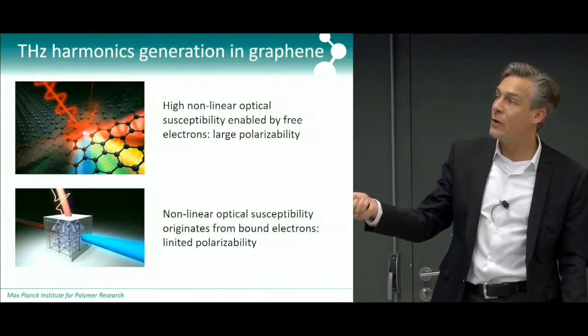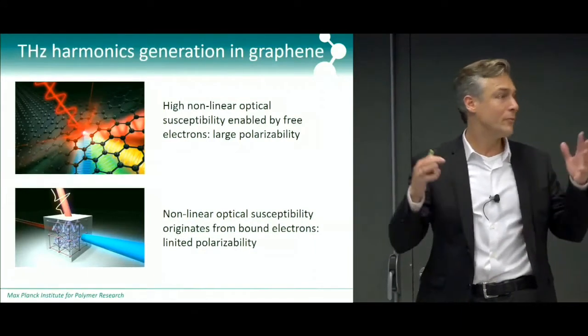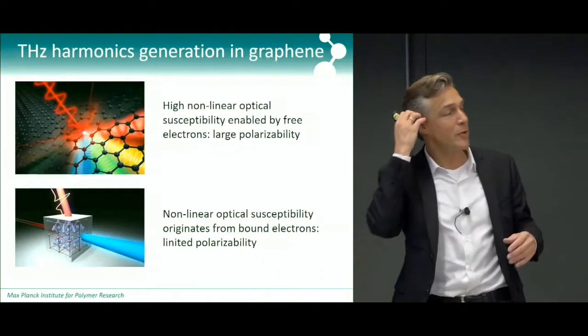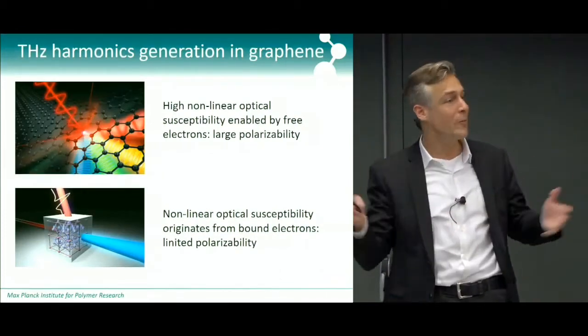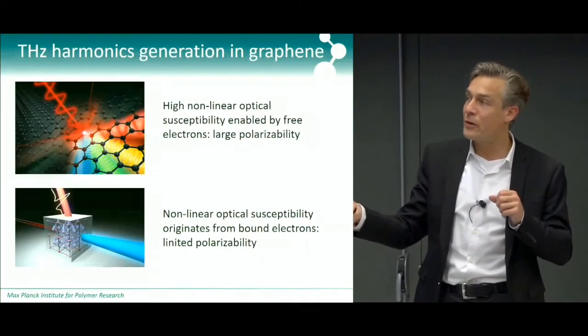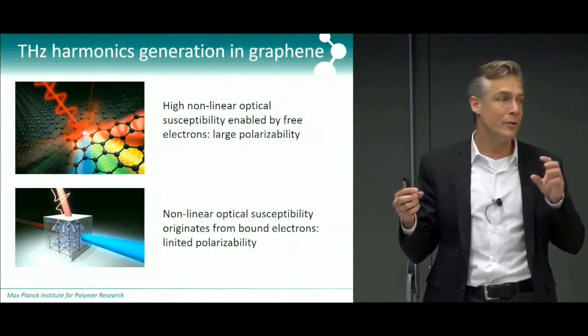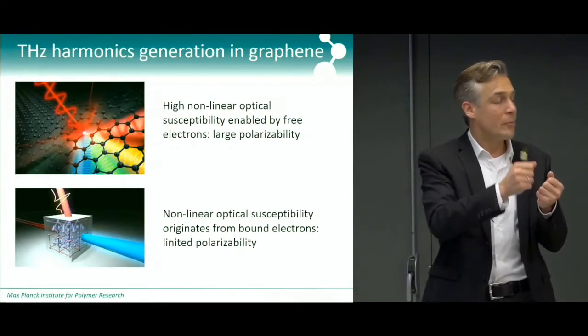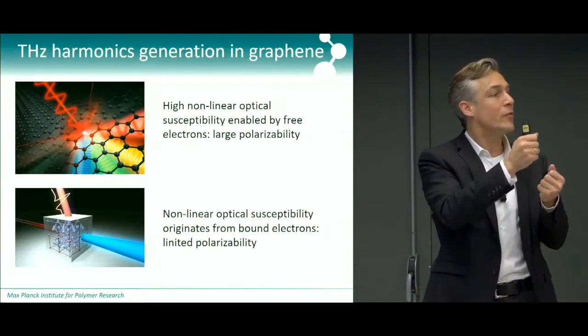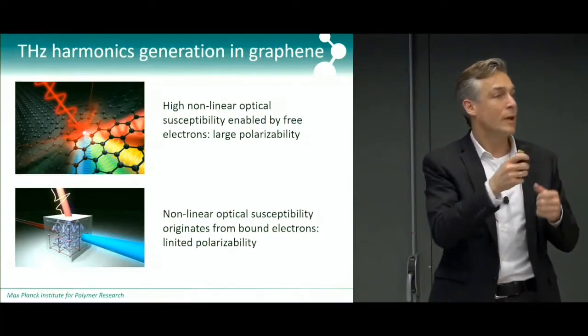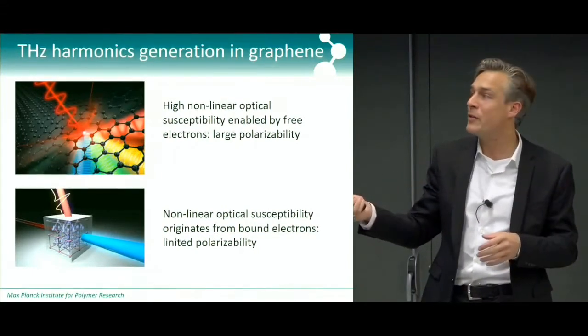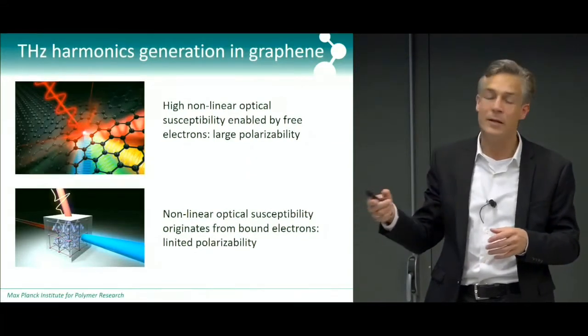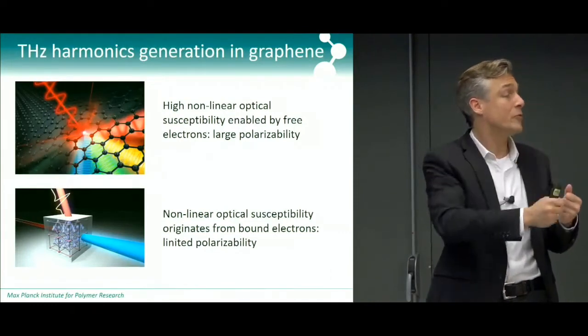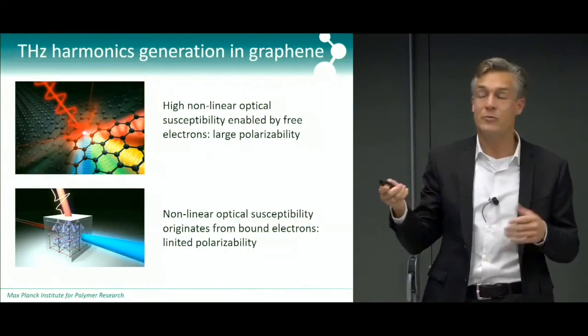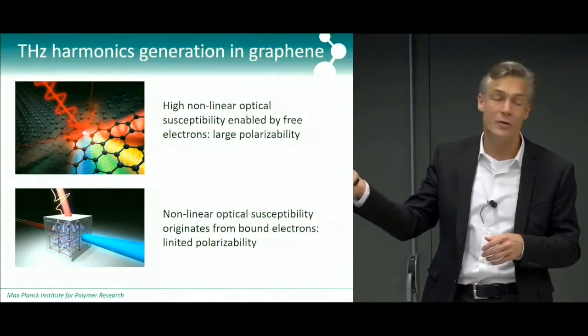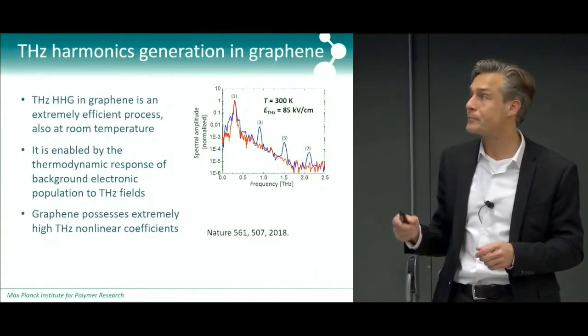If you compare that to a nonlinear crystal, like many of you who do laser spectroscopy work with BBO crystals or lithium niobate crystals, those nonlinear susceptibilities rely on the nonlinear displacement of electron wave functions that are bound electrons. And so it's not a surprise that those have a much smaller polarizability and that you need to apply much stronger fields to get into the nonlinear regime. And so this is what allows this very high conversion efficiency in the monolayer graphene.